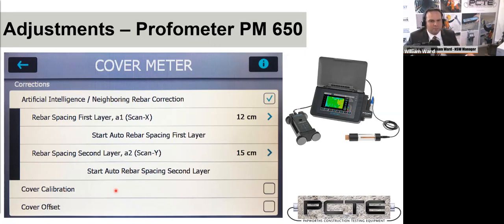Now, cover calibration actually allows you to go to a known depth of reinforcing steel of any particular construction and use that to calibrate. So as I said, this is great for things like precast applications. You can go across an anti-burst cage where there's lots of steel, but if you've got a drilled conformation or even before casting, you could calibrate the cover measurement of that detail and then come back to the same detail after the concrete is cast and take your cover depths with a calibration function.